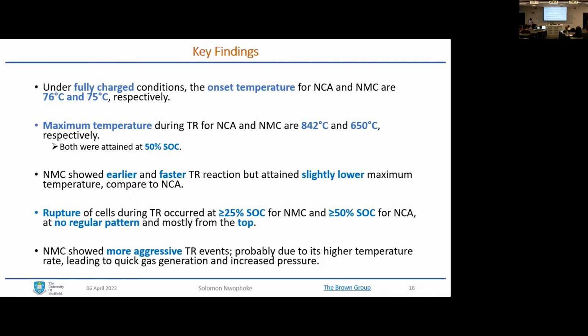Then the next point is NMC showed an earlier, faster reaction, but attained a slightly lower maximum temperature compared to NCA. Then thermal runaway occurred at 25% state of charge or above for NMC and 50% state of charge and above for NCA, with no regular pattern. Then NMC showed a more aggressive thermal runaway event, probably due to high temperature rate, leading to quick gas generation and increased